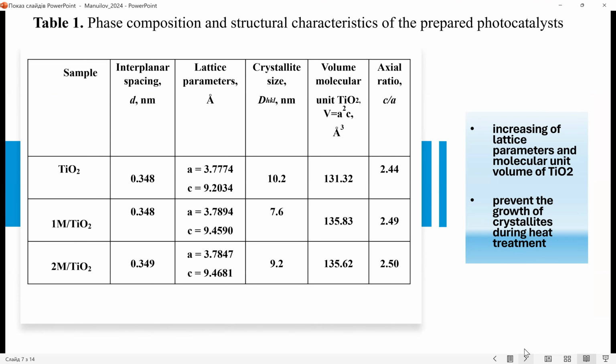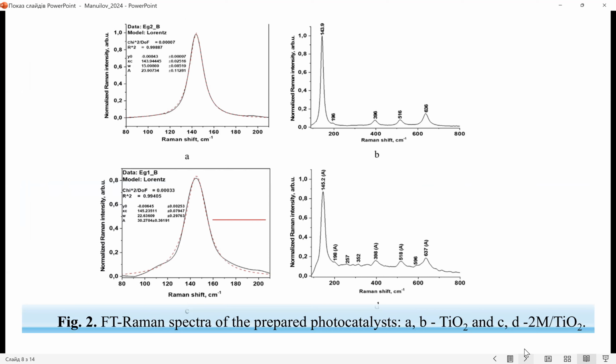Indeed, we can see an increase of lattice parameters and unit cell volume of titanium dioxide, and such modification prevents the growth of crystallites during heat treatment. We also investigated these samples with Raman spectroscopy. We use the spectroscopy to determine the stoichiometry and the size of nanocrystallites in the prepared titanium dioxide.